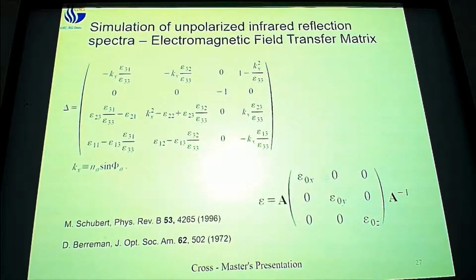However, in the z direction, my dielectric function is different. To complicate matters even further, we assume that my crystal structure is not aligned vertically with my system structure. If I take a look at my Fourier transform infrared spectrometer, I have a plane sitting like this where I put my sample, and this is up, but that may not be up for my crystal. And I know it's not up for my crystal because of the substrates that we bought. So we have a tilted axis, which is what these A functions do here. These A matrices will rotate my dielectric function so that my dielectric tensor now speaks to the actual dielectric tensor that the light is experiencing in the laboratory reference frame. That feeds back into here, and this K value is just the component of my wave vector that's parallel to my surface.